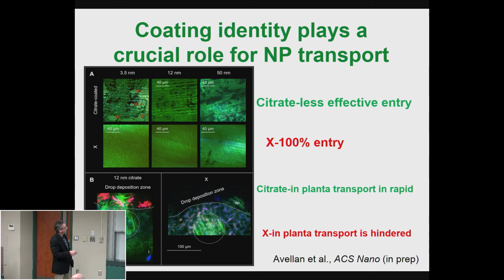And what we found is, if you put citrate-coated gold on top of a leaf and come back after 7 days, you get a bunch of citrate-coated gold on top of the leaf. That's what that black stuff is in the microscope. It's a little bit aggregated. So some has gone in the leaf, I'll show you, but not so much.